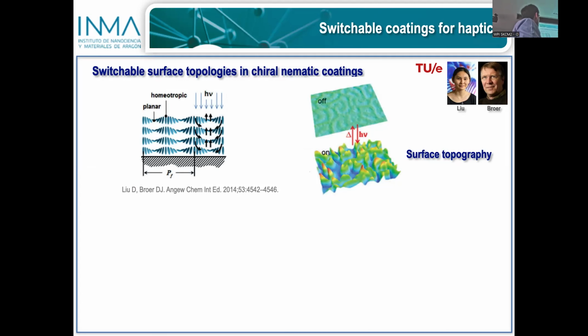So if we now heat, or expose to light and heat, this type of sample, then according to the previous deformation rule, we will have a contraction in these areas and an expansion in these areas. And this is seen in this cartoon, in which you see that the texture blows up from the substrate, which is potentially useful in optics applications.